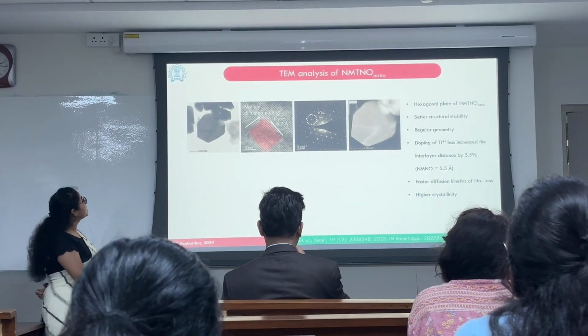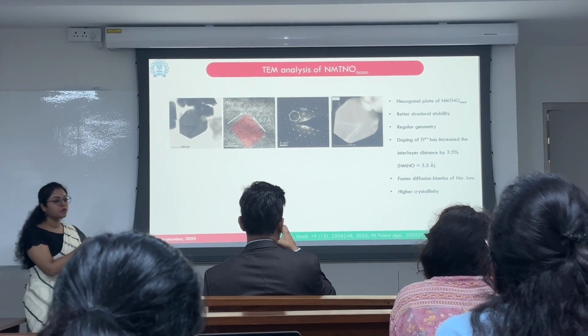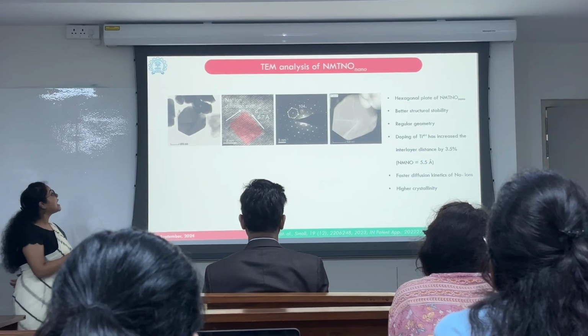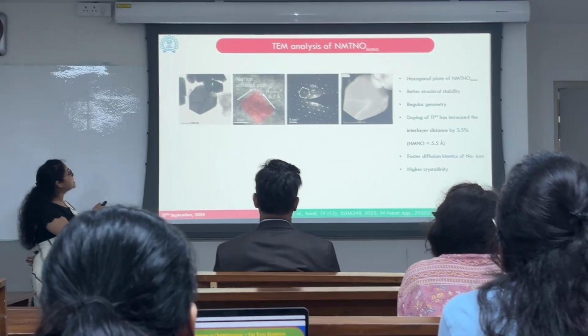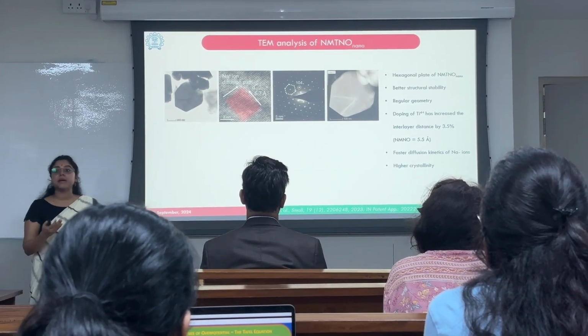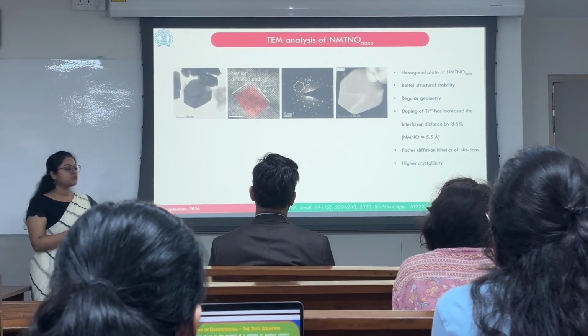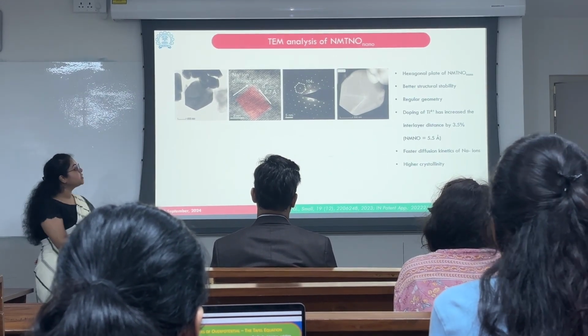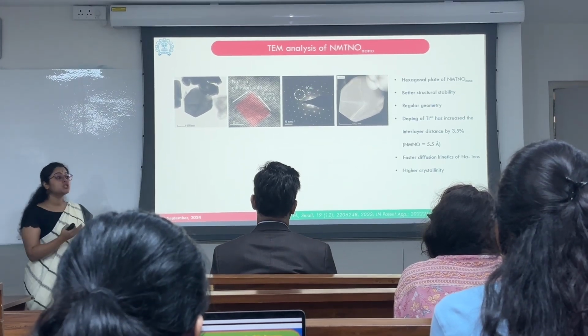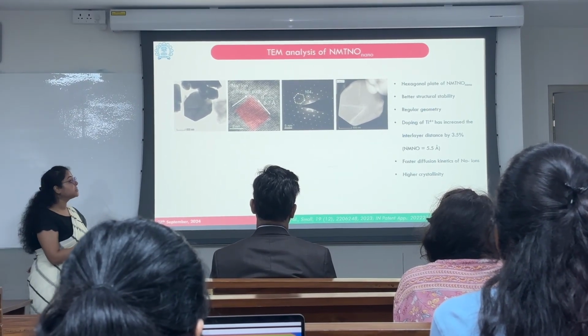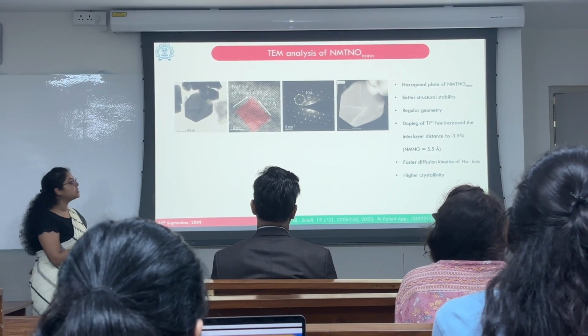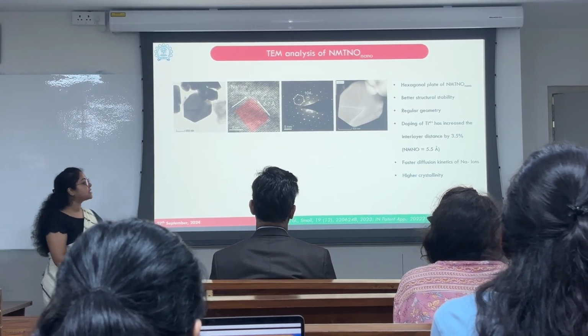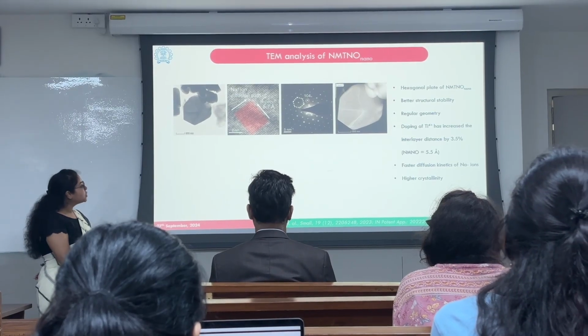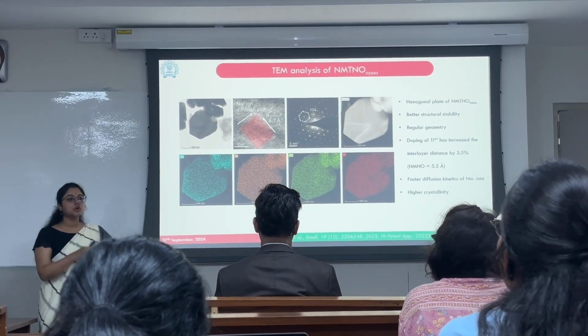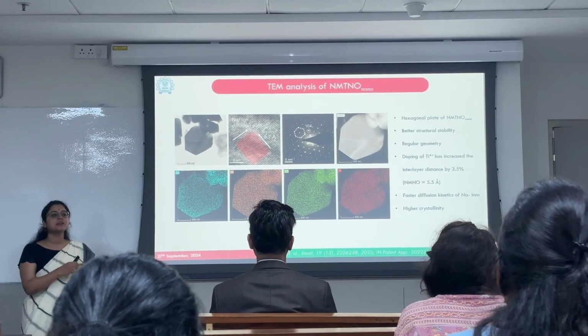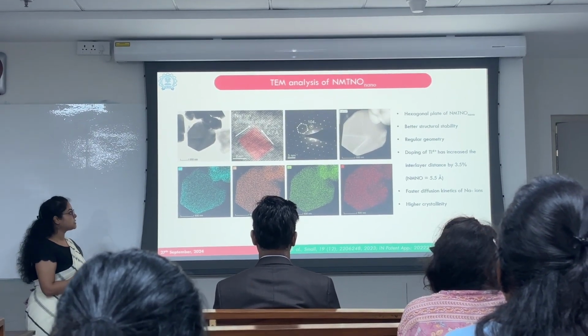Through the transmission electron microscopy, we actually saw the primary crystals in a better way. We saw that the primary crystals have hexagonal plate-like morphology as seen in the SEM as well, and they were seen to be quite well interweaved with each other, which suggests a better structural stability and a regular geometry. Through the high resolution TEM, we found the d-spacing to be around 3.5% higher than that of the pristine cathode material, which suggests better diffusion kinetics of sodium ions. Through the elemental analysis, we observed that even in the primary crystals, the elements are uniformly distributed.